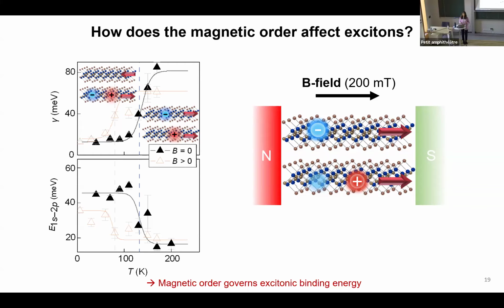Why is this happening? Because at 80 Kelvin, the magnetic field strength is sufficient to combine with the thermal effect, flip the spin orientation from the antiferromagnetic phase to the ferromagnetic state and help delocalize the electrons already below the nominal Néel temperature, right? So we demonstrate that it is indeed the magnetic field which governs the exciton properties, the internal structure of our excitons. Any questions?